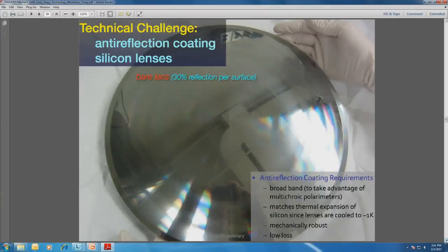So by playing with the filling fraction, you can realize any value you want. Now, if the pitch between the various objects becomes too large, you'll diffract. You could look at that as a feature or a problem, depending on how you view it, but it is a reality. Because as you go to really short wavelengths, the material is going to scatter light, which could help you or hurt you, depending on how you did the rest of your optical design. But you need to keep in mind what's going to happen out of the band.